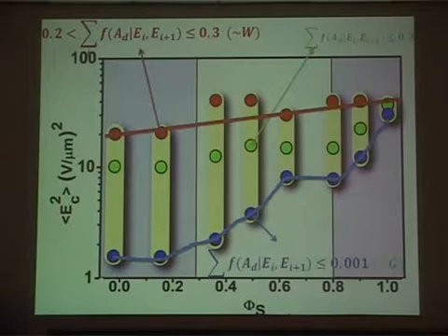But suppose I ask the other question. I chose not the 0.1 as just the initiation, but I said, okay, when 30% of my film has got delaminated, what happens then? It so happens that that's not so dramatic. Yes, it increases, but it doesn't increase that dramatically. And what it tells you is, these two are measuring two different parameters of my experiment. What this measures is the elasticity of my thin film. It tells you that the first crack is where the elasticity of this thing has failed. Plasticity has come in. This tells me where the system has actually overcome the maximum pinning of the potential. So I can have a small failure.